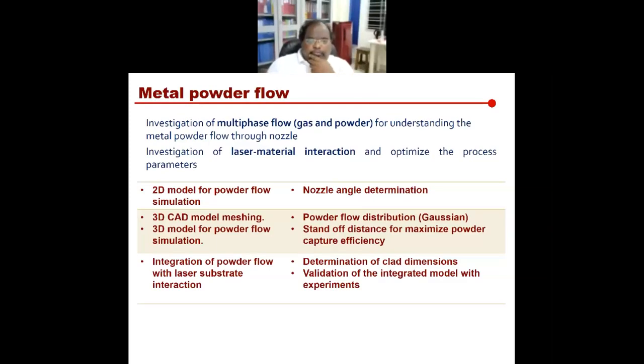So one of the major issues was that since none of this information was available, what we did is a little investigation in multiphase flow, and also some laser material interactions. And of course, we did this 2D model for powder, and based on that we tried to get the nozzle angle determination. Then powder flow distributions, and basically the determination of the clad dimension.